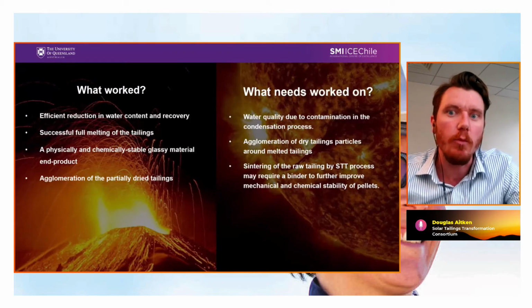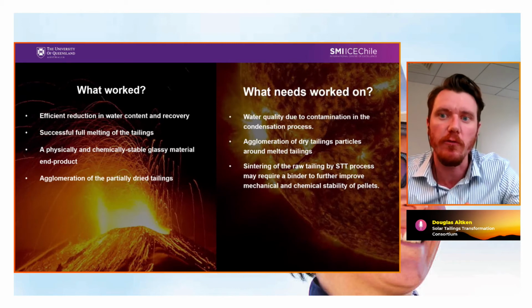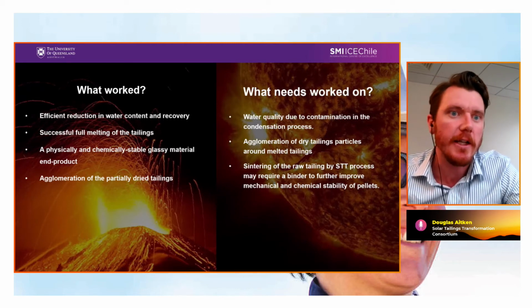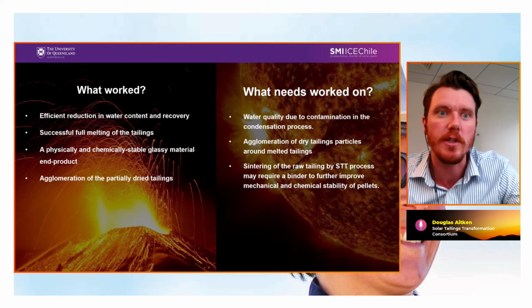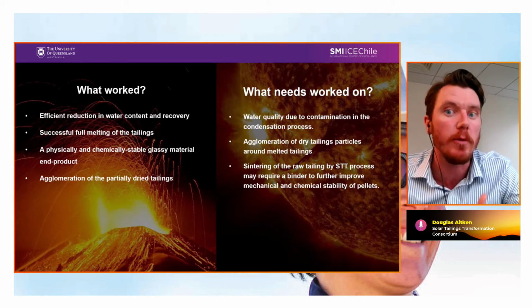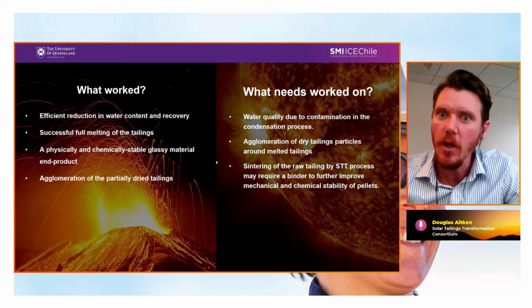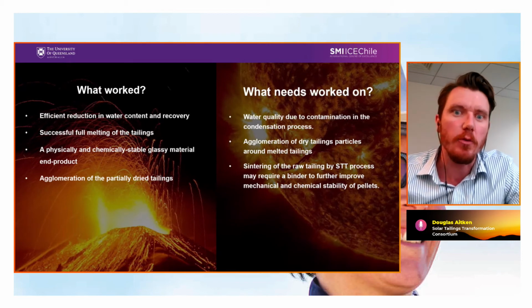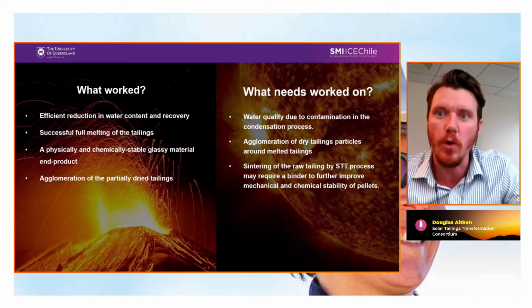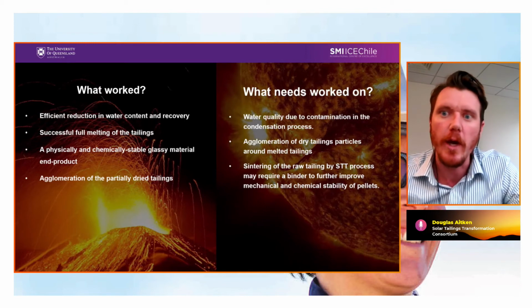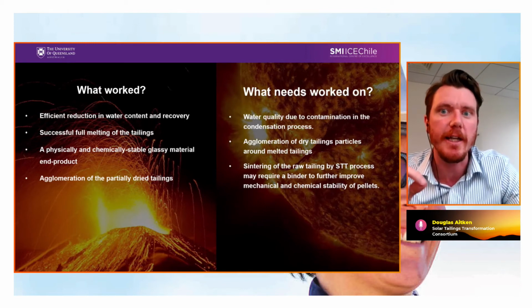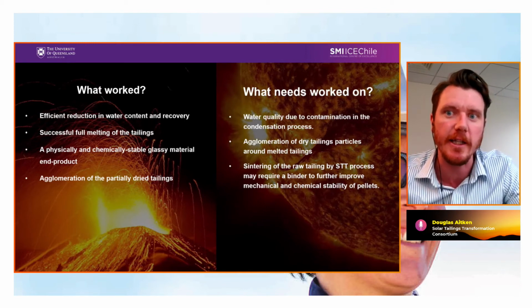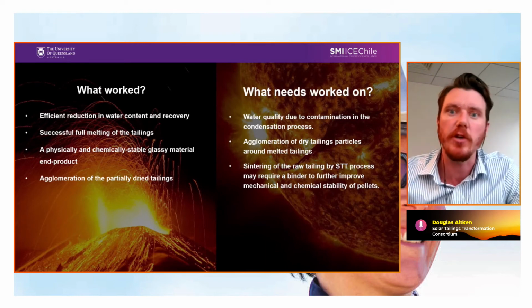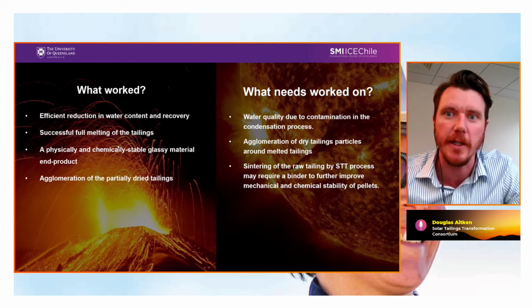So what worked? We were able to achieve a high reduction of water content and removal of the water. We were able to melt the tailings using the solar simulator. We were able to produce a stable glassy end product, and we were able to agglomerate the dried tailings into briquettes and pellets. What needs to be worked on? The water quality issues that we found with the recovered water. We need to find a way to achieve agglomeration of the dry tailings particles around the melted tailings fraction, and also improve the sintering process to achieve the required stability.